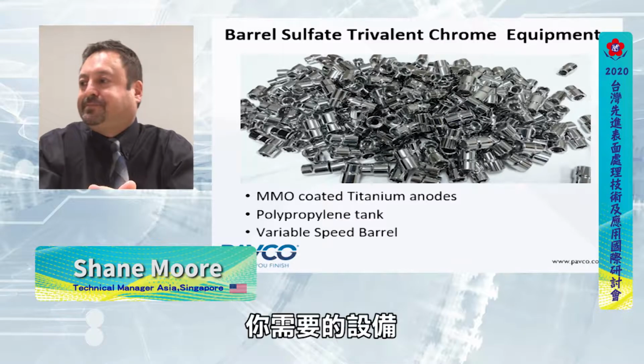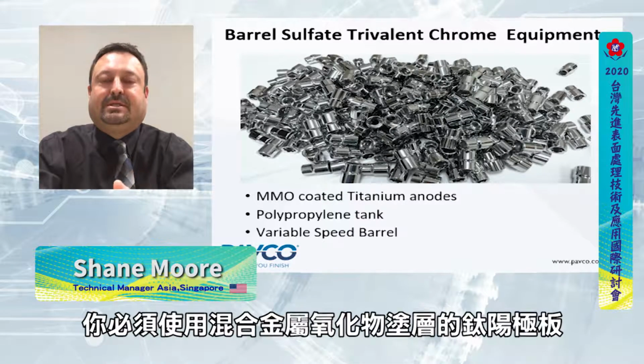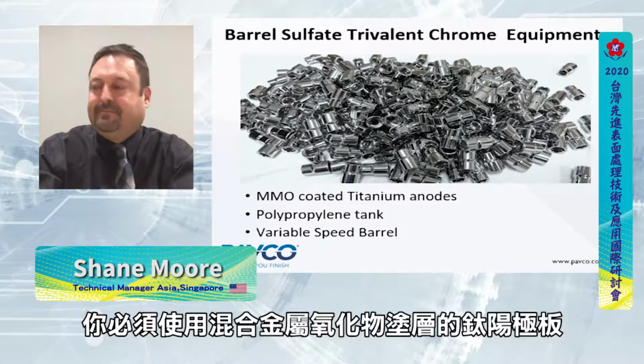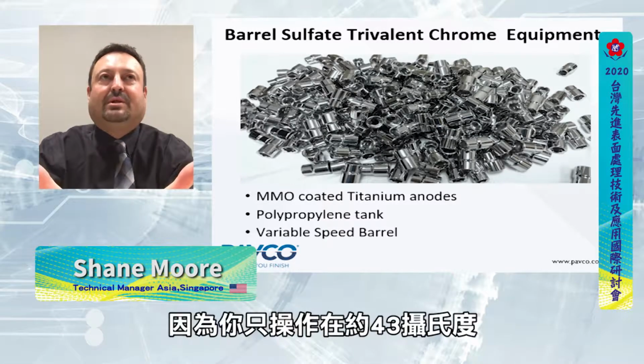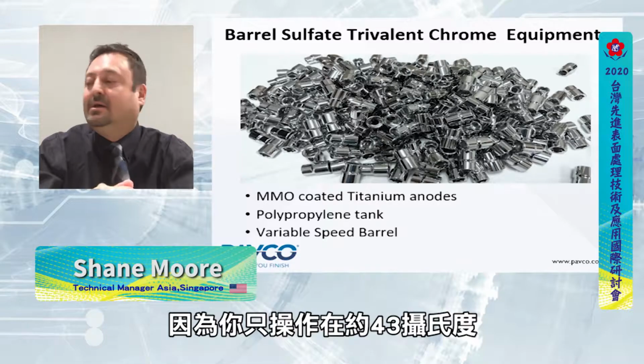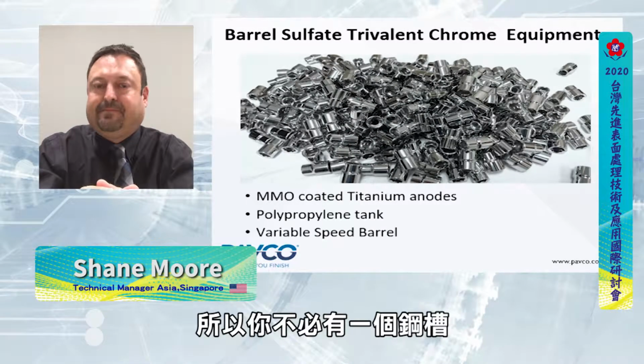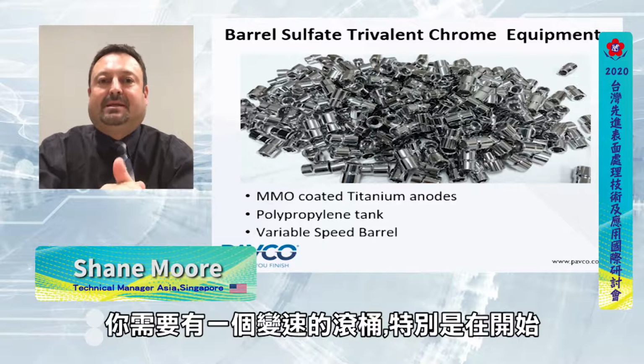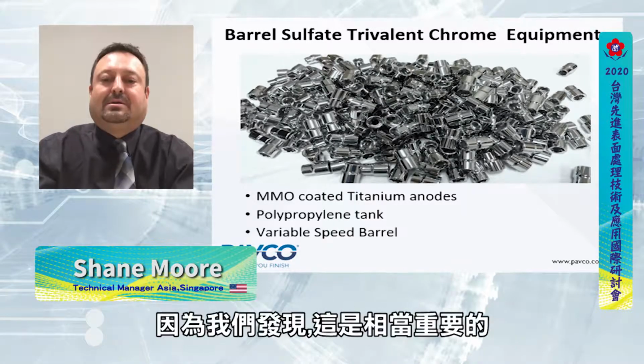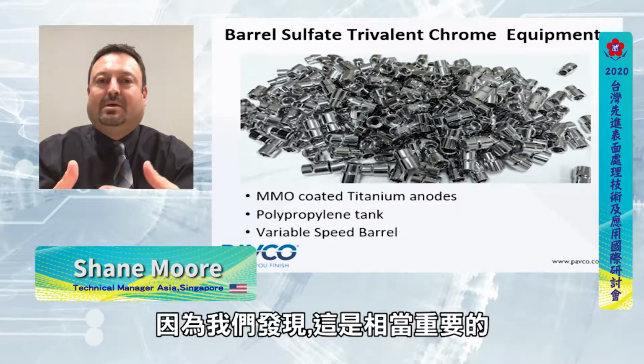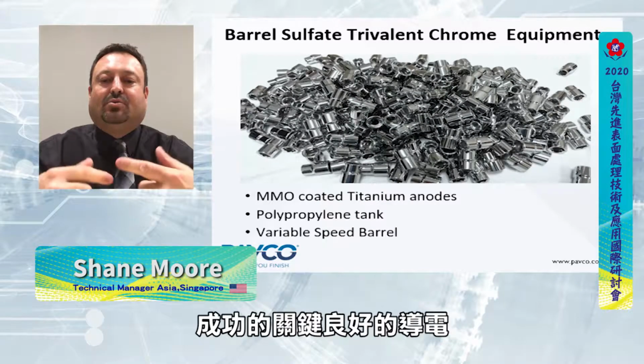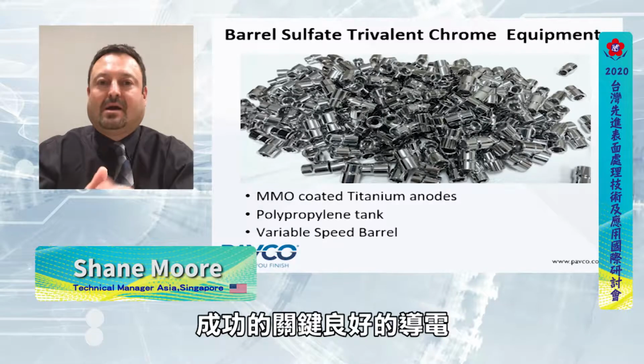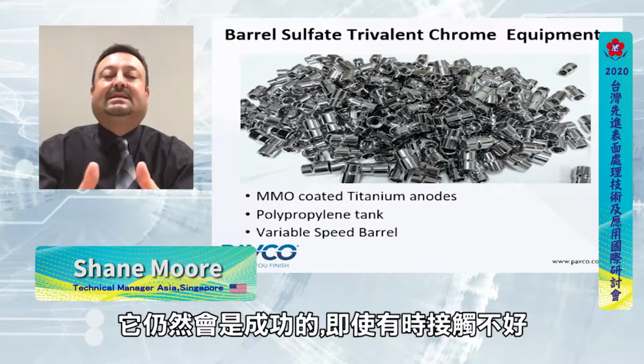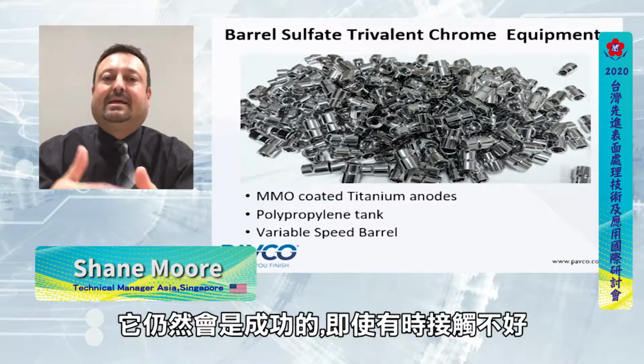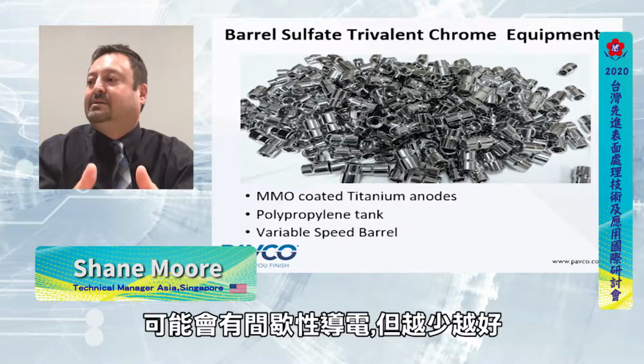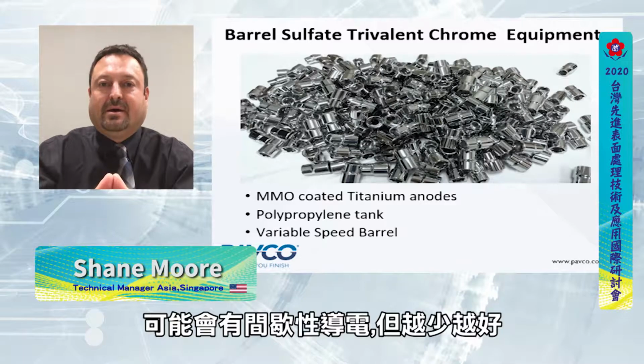The equipment that you need. Like I said, you have to use the mixed metal oxide coated titanium. A polypropylene tank is fine because you're only running at about 43 degrees Celsius. You really need a variable speed barrel, especially in the beginning, at least when you're designing the line, because we have found that's pretty important. The key to success is you want the least amount of making and breaking contact as possible. I mean, it's still successful even if it does make and break contact. It can take intermittent contact, but the less that this happens, the better.